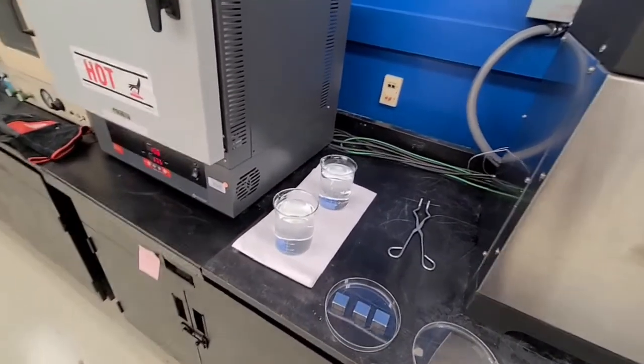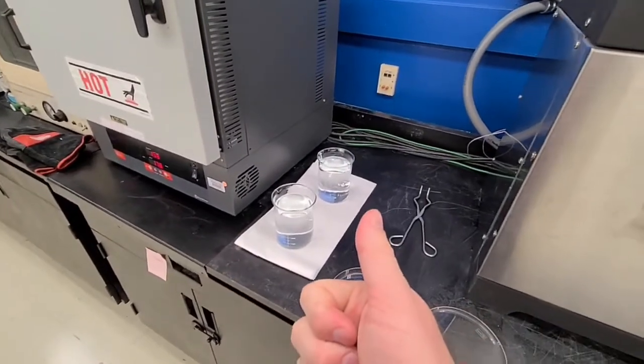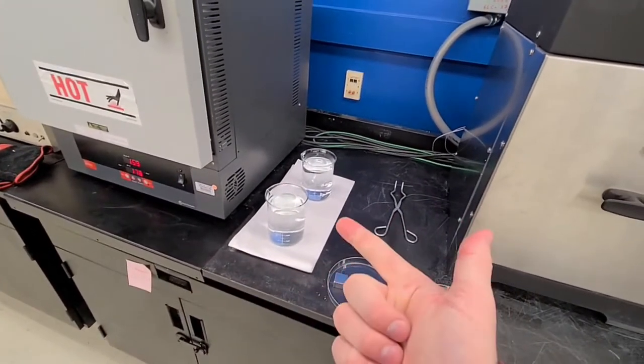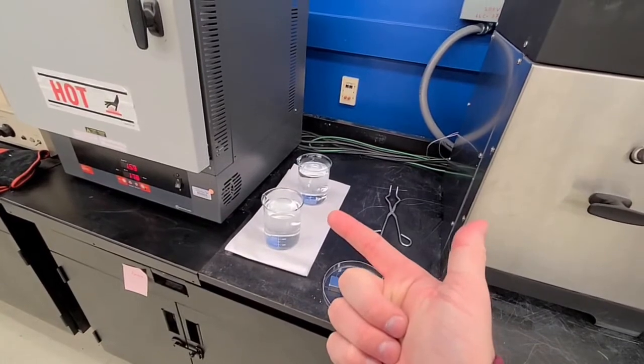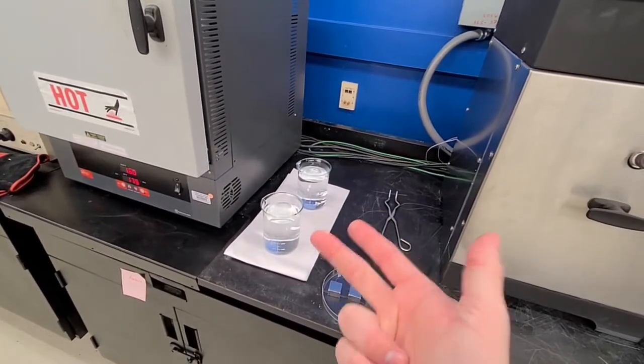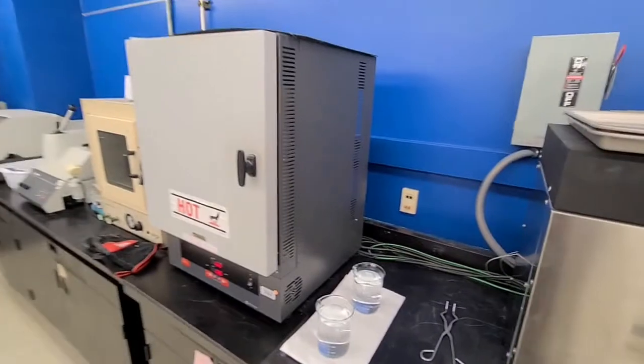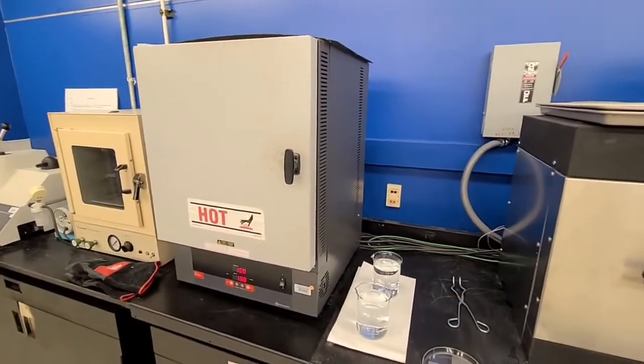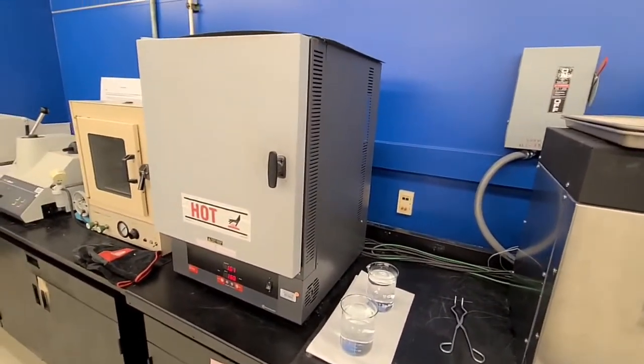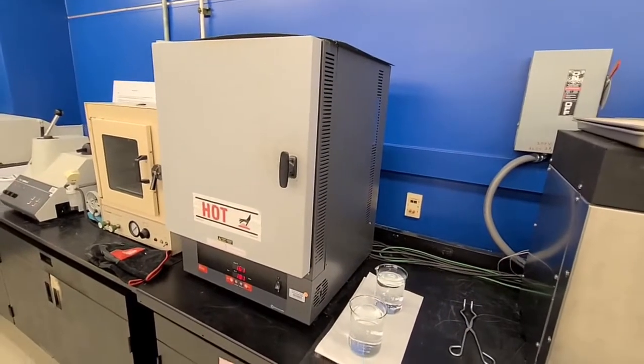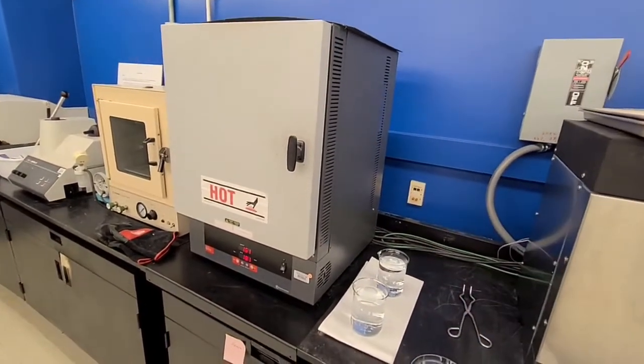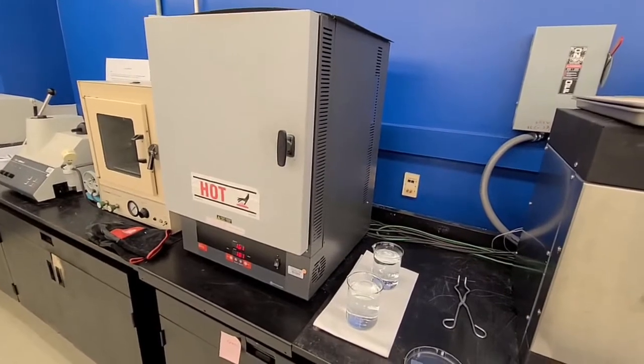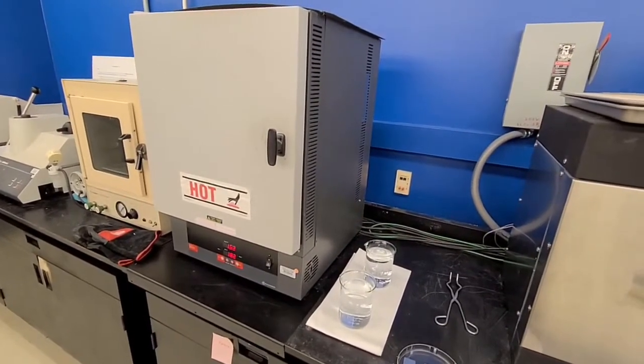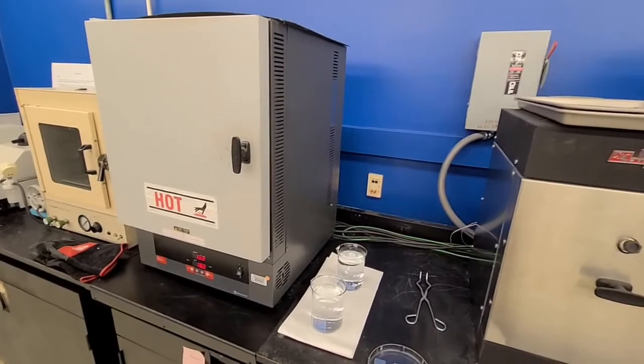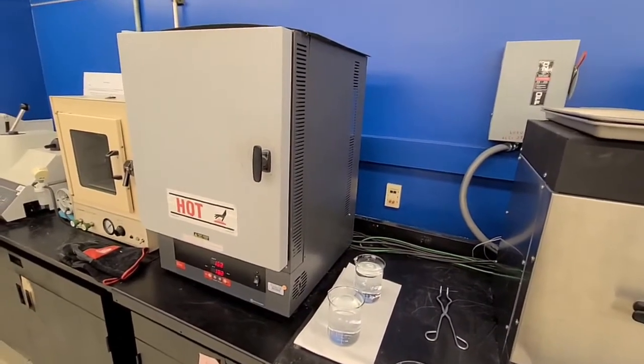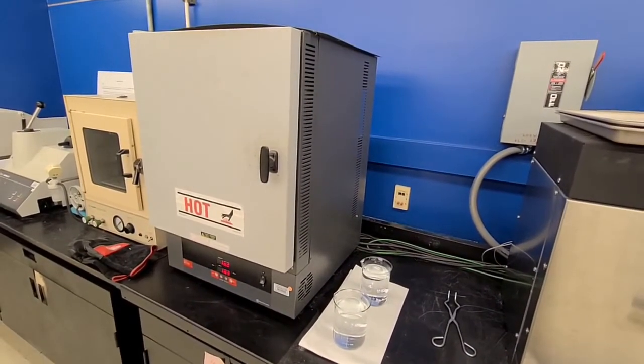So remember, we have a sample that we're going to let do natural aging at room temperature, a 150 degrees annealing treatment, and a 200 degree annealing treatment. The issue is that I have 1 furnace, so I can't do those 2 annealing treatments at temperature at the same time. So what I'm going to do today is 2 different samples, our room temperature natural aging and our 200 degrees C treatment. I'm going to do all my time points, measure my hardness, and then come back on a different day to do the 150 degrees C sample.